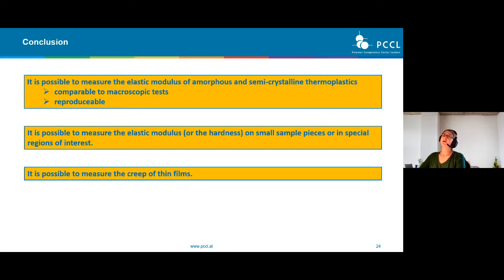The conclusion of my presentation is that it is possible to measure the elastic modulus of amorphous and semi-crystalline thermoplastics, which are comparable to macroscopic tests and which are reproducible. Furthermore, it is possible to measure the elastic modulus or the hardness on small sample pieces or in special regions of interest. And it's also possible to measure creep of very thin films.